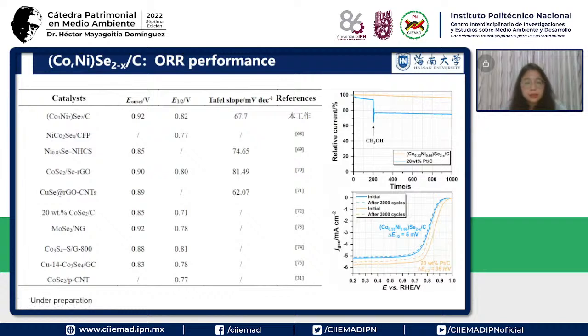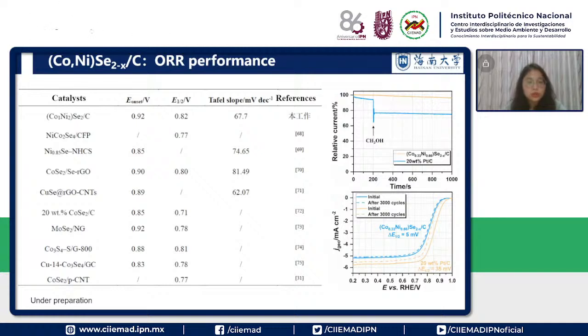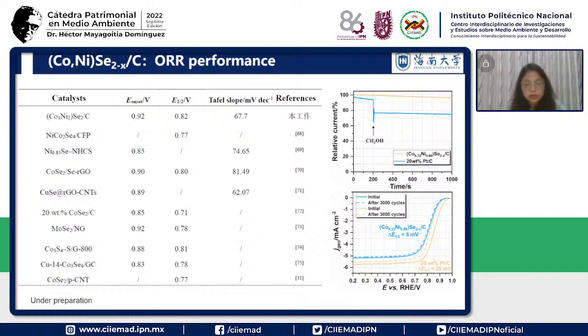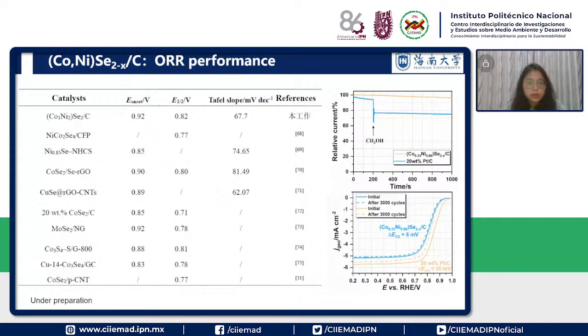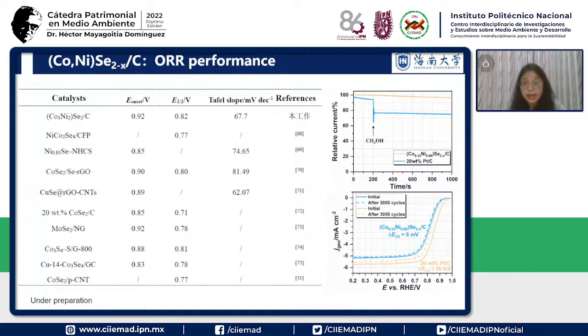The next slide here, we compare our material. The best one is the mole ratio 1:2 selenide supported on carbon in alkali towards ORR, compared to the other materials reported in the literature. And we can see our material shows a comparable activity performance. Besides the activity, we also want to know about the methanol tolerance and the stability.